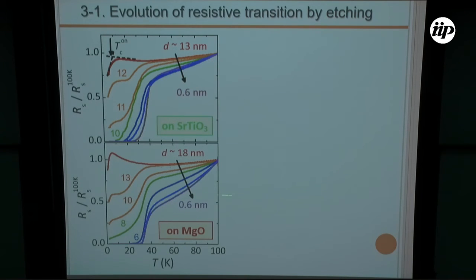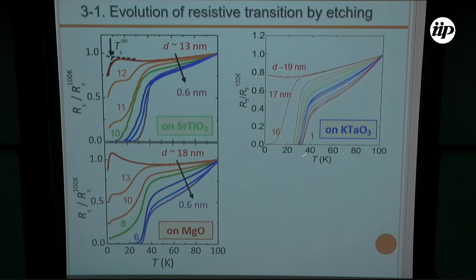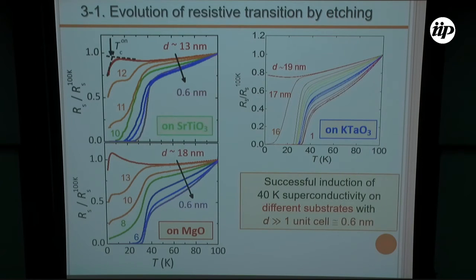Surprisingly, we obtained a similar result on the MgO substrate and also on potassium tantalate. So these results indicate that strontium titanate is not a unique substrate to obtain high temperature superconductivity. And here we note that the critical thickness with a single transition is much higher than the 1 unit cell thickness, and this value depends on the substrate, which we will discuss later.